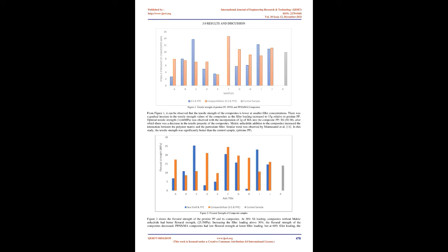Paraffin wax was added to the mold. Before placing the mixture in the hydraulic press, 10 samples of compatibilized composites and 10 samples of composites without compatibilizer were produced in a dumbbell shape. The samples' mechanical properties were analyzed. Table 1, Formulation for Polypropylene/Cockle Shell Composite without compatibilizer.